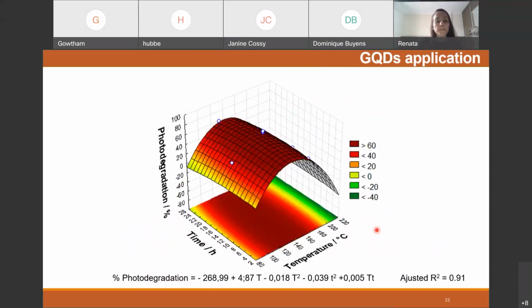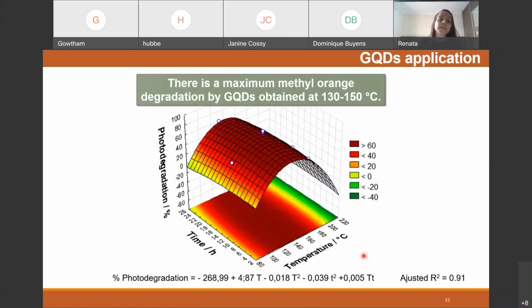Finally, we have a mathematical model of our data generated by the experimental design, and it is possible to observe that there is a maximum methyl orange degradation by graphene quantum dots when the graphene quantum dots were obtained in this range of temperature.